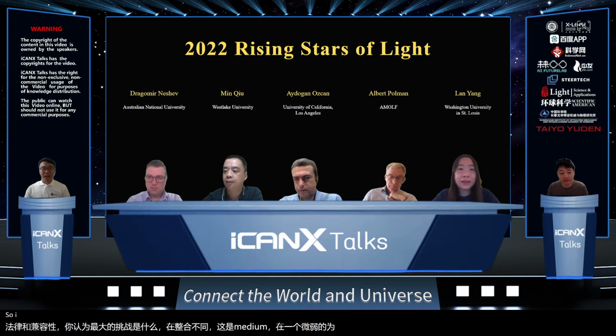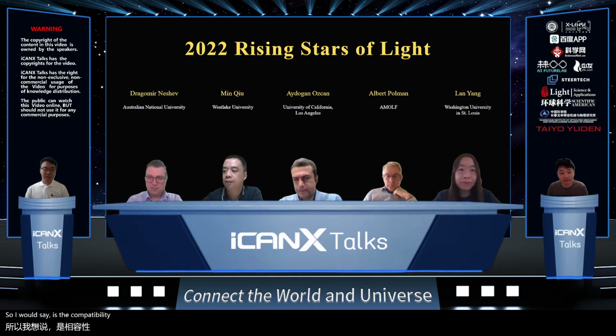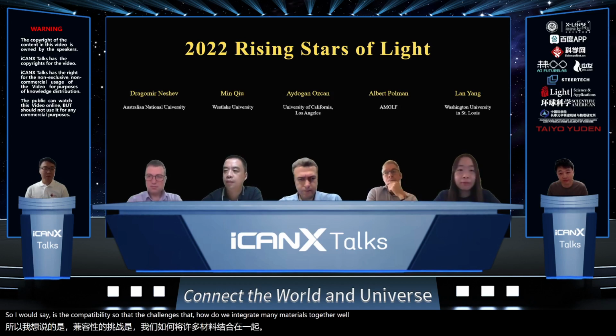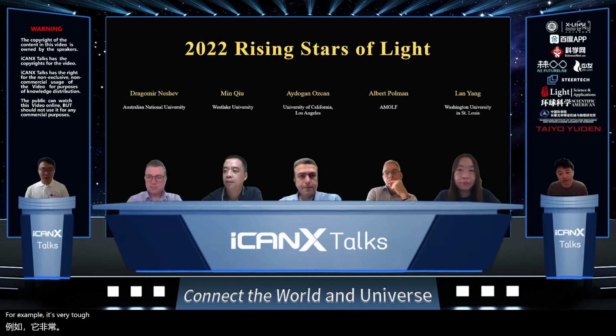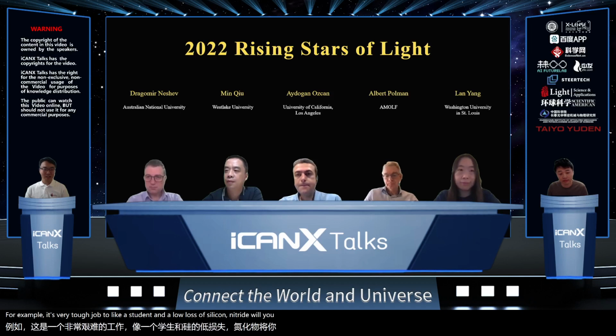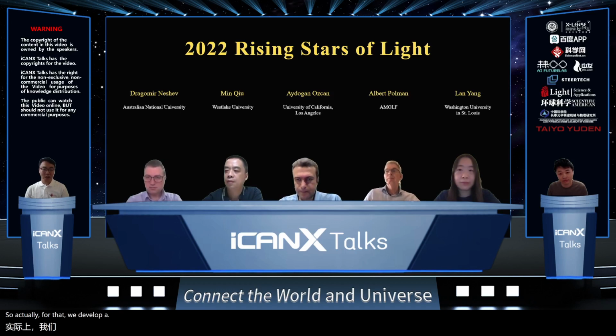I would say it's the compatibility. The challenge is how to integrate many materials together while maintaining their desirable properties. For example, it's a very tough job to maintain the low loss of silicon nitride while you put those III-V materials onto it. For that, we developed a lot of special technologies to protect the silicon nitride layer and avoid the degradation of the performance of the nitride waveguide itself.